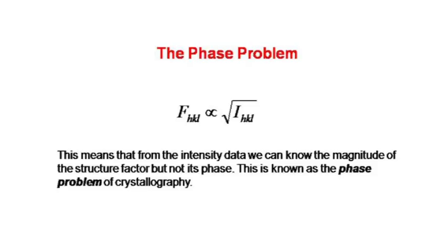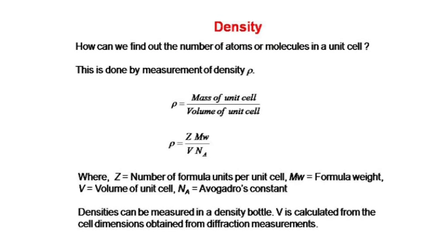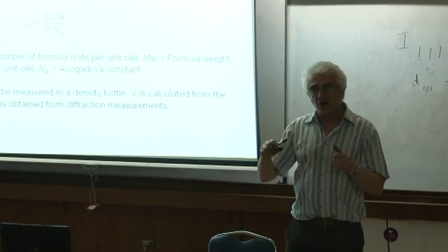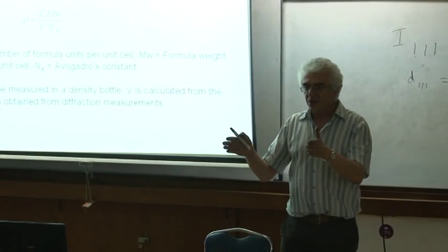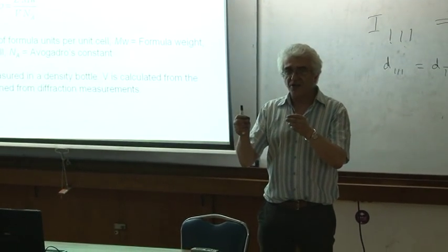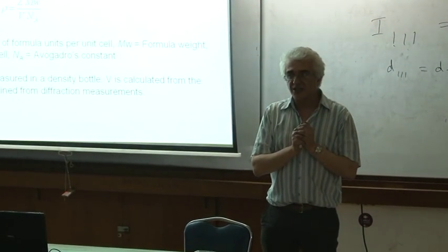So, when we're doing crystal structure analysis, we use every bit of information that we can find to try and get out the crystal structure. And what we then do is we have our observed data. We usually are working with intensity squared or F observed squared, and then we're trying to work out what the phases are by taking a model and using a least squares refinement to try and fit the observed data.